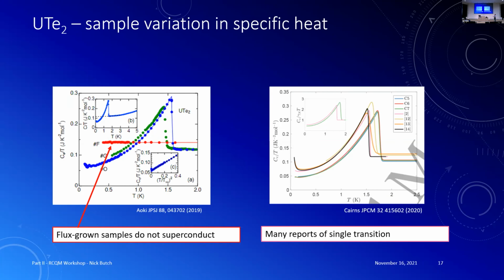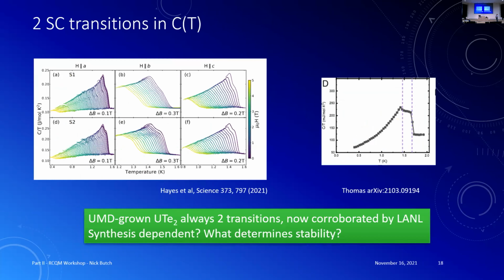It's also true that people knew from the old days how to make samples that are not superconducting. But it seems like if you get something like this, if you got a superconductor, it's already a 1.5K system. You can make crummy ones that have lower TCs, but they're not going to look like this. Now, also there were many reports of, we only get a single transition. And the first thing that we'd have to say is that it took a little bit of work to see the double transition. You had to do smaller temperature steps in your heat capacity measurements. So unless you're doing that, and I don't mean that people weren't, it's not sufficient to say that, oh, we don't see that. Okay.